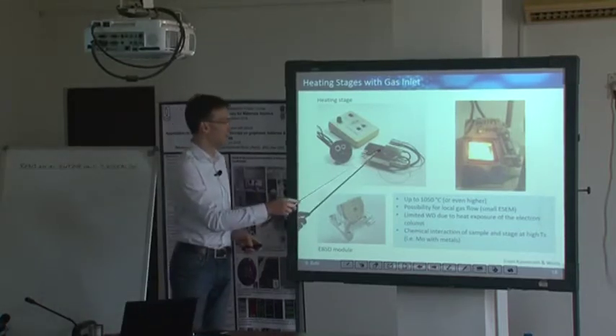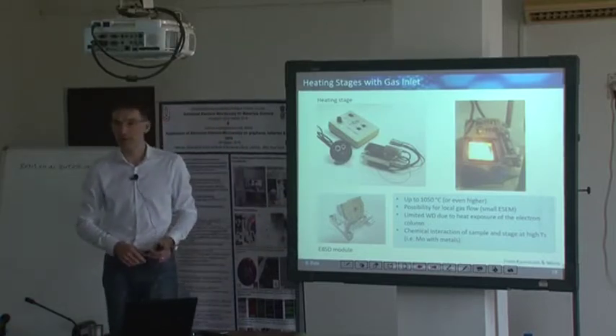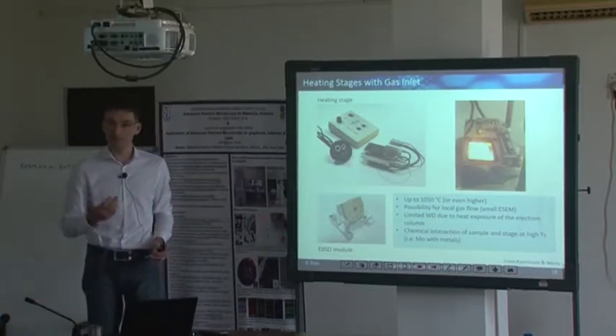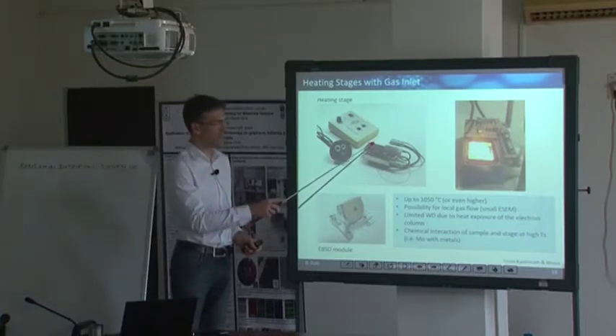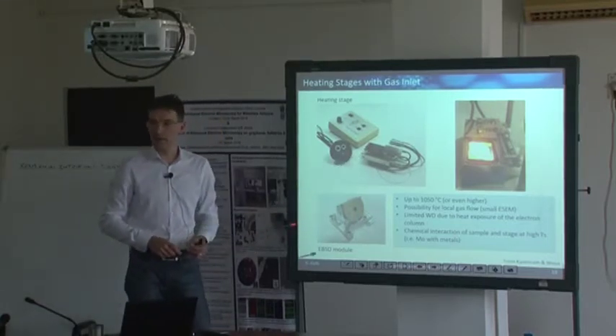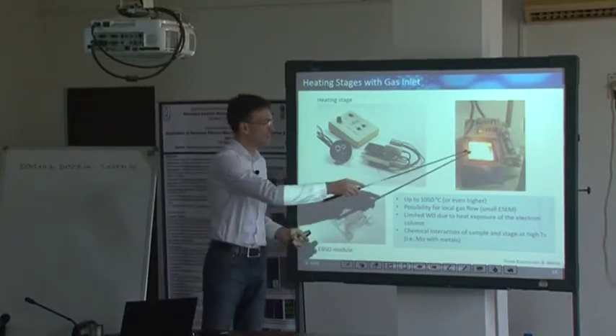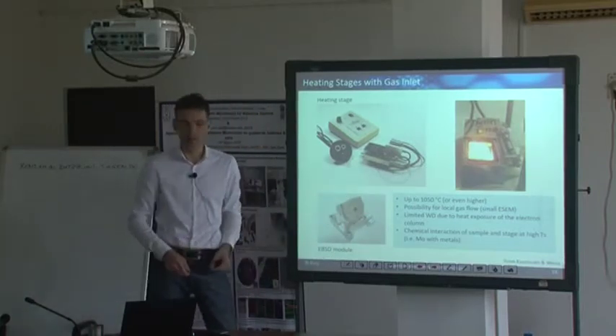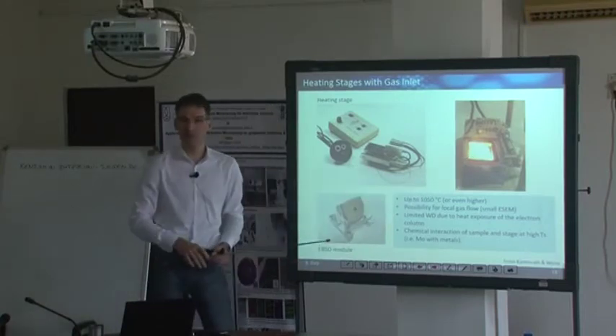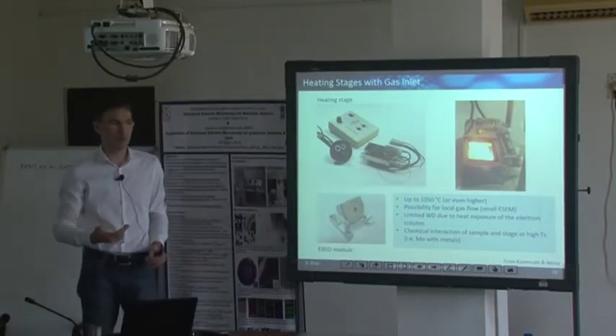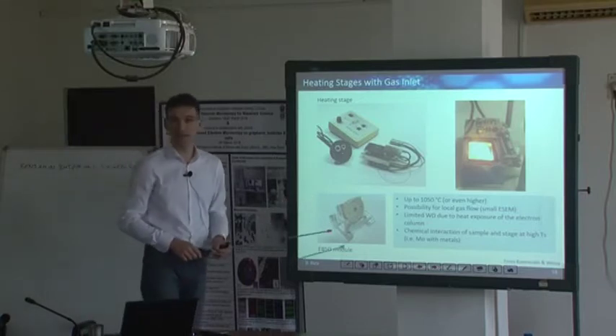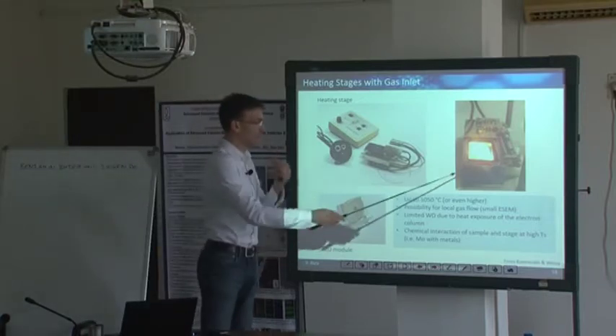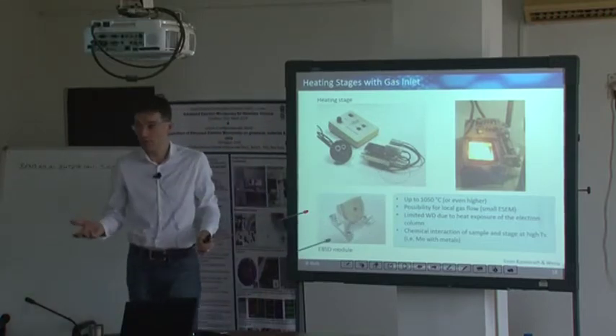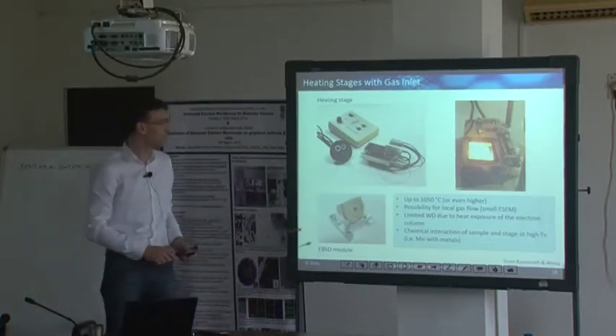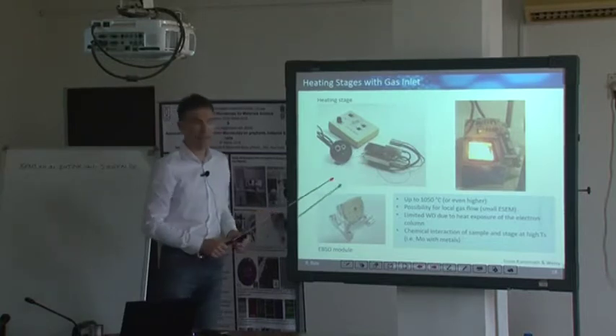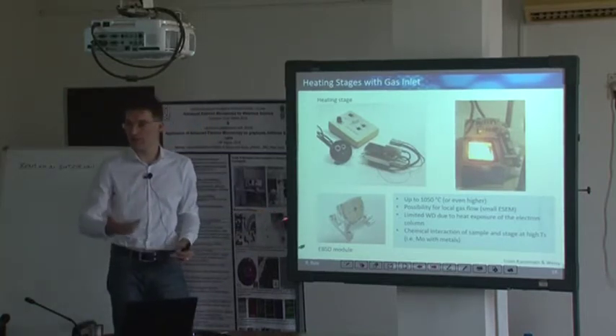If you work under a certain gas environment, you always have to keep in mind that your sample temperature might differ from your preset heater temperature, because you only measure the temperature in there, and you just watch the surface. But if you have a gas environment at very high temperatures, there might be thermal losses. At very high temperatures we have radiational losses, so the sample surface might be colder. And on the other hand, in an environment you have convection and transfer to the gas.